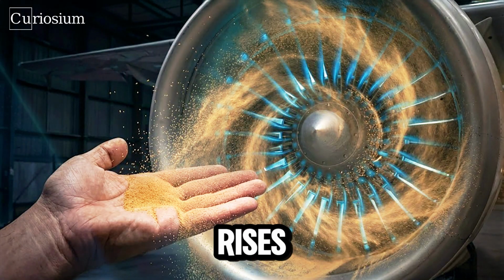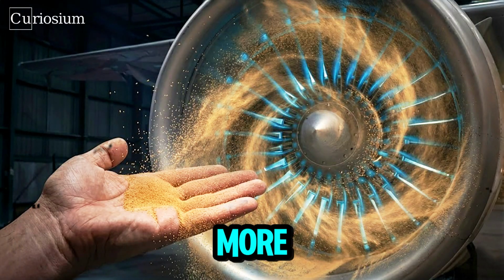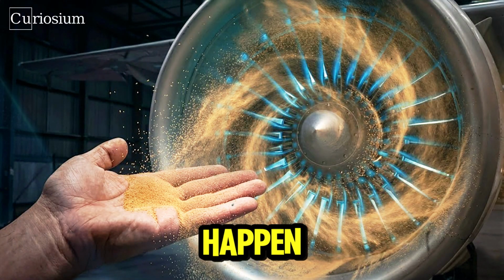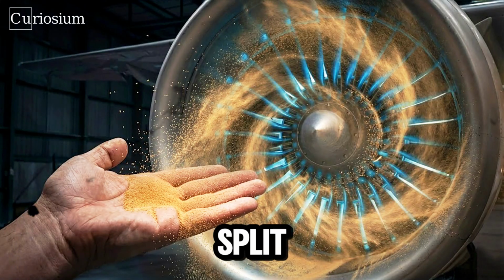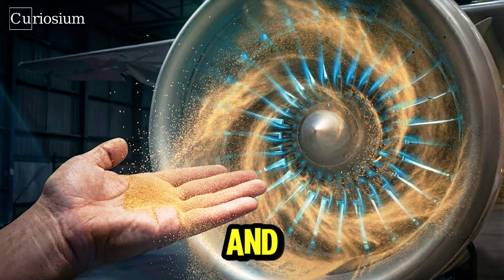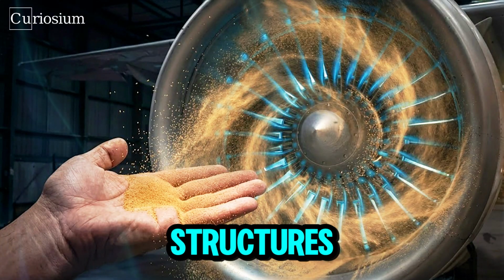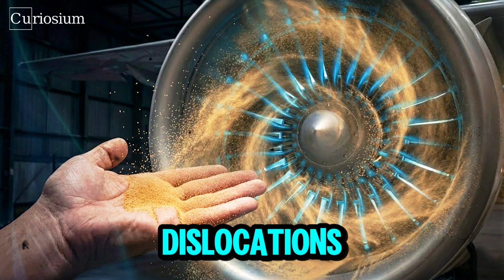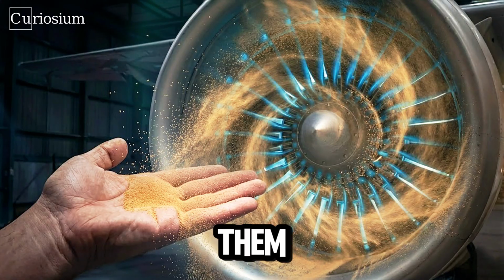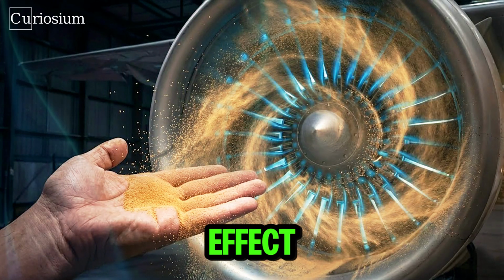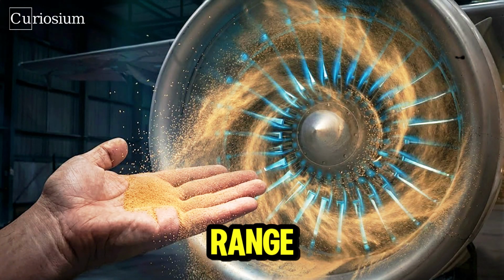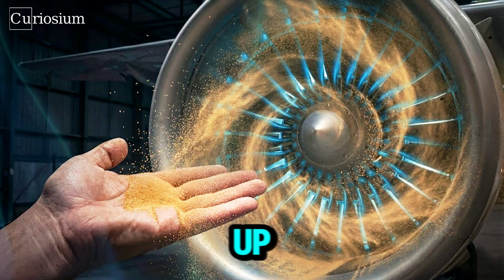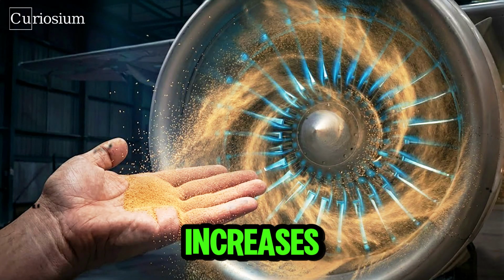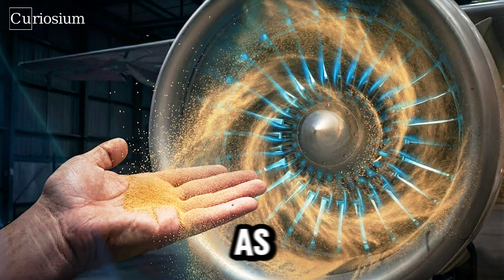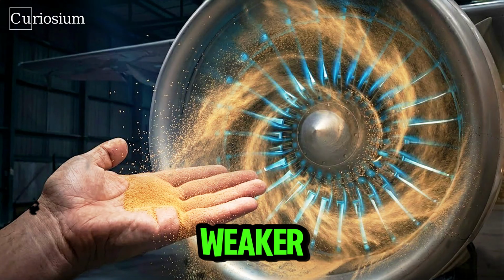As temperature rises, atoms vibrate more, and something even more interesting can happen. Dislocations can split, cross onto different planes, and in some cases form paired structures that have to move together. These are called super dislocations. Creating and moving them takes a lot of energy. The effect is that, over a certain temperature range, adding heat actually locks up dislocation motion and increases the alloy's strength, even as steel and titanium are becoming weaker.